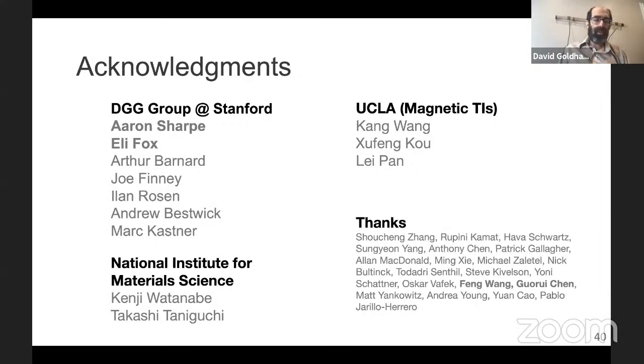Yeah, so those are all excellent questions, Reyes. And I have to say, my first answer is we don't know. But I can do a little better than that. First of all, we strongly suspect that the size of the domains is on the order of a micron, because that's the size of our Hall bar, and you can see that there are some really big jumps in the Hall resistance signal, and those would only happen if you think about edge states of quantum Hall going around the periphery of a domain. You're only going to get a big change in the signal if that domain basically ends up giving you a path that spans from one edge of the sample to the other.